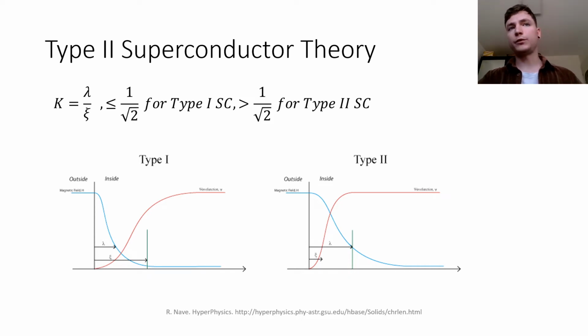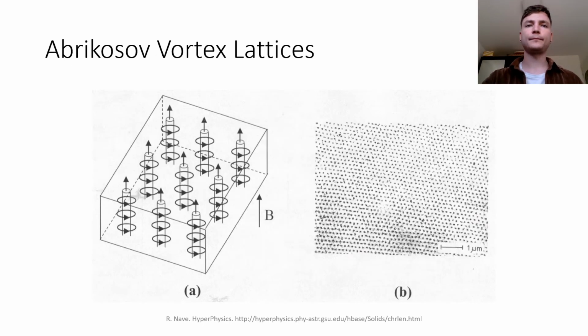He then showed these results to Abrikosov, and he considered the case for the Ginzburg-Landau parameter to be greater than 1 over square root 2 and calculated the critical fields. And his results fit the data perfectly. And he investigated this case further, and he found that the periodic distribution of the magnetic field inside the superconductor in this newly formed phase would minimize the energy if they arranged in a lattice of magnetic flux quanta, which is shown here.